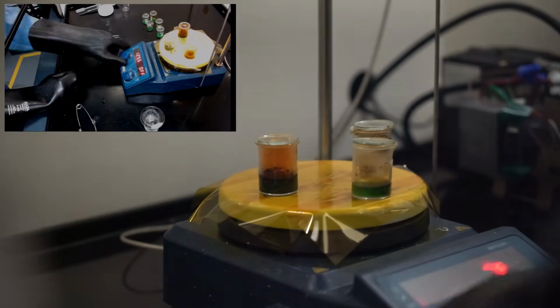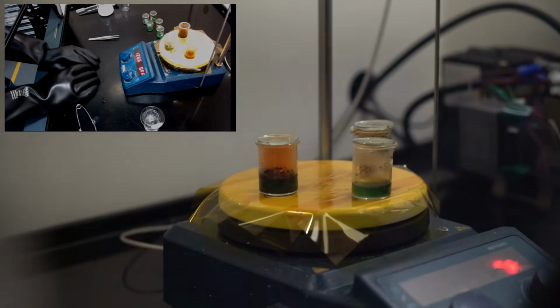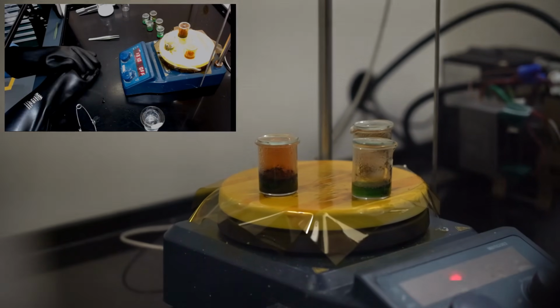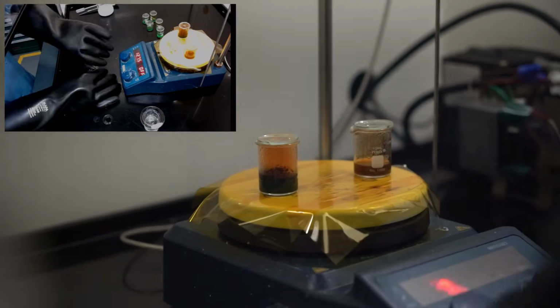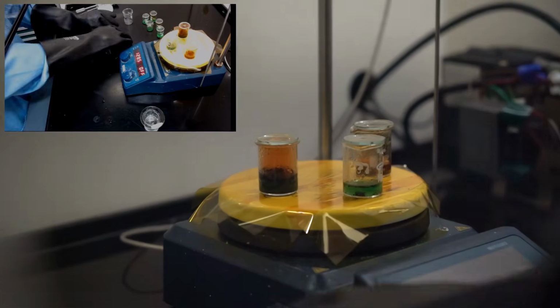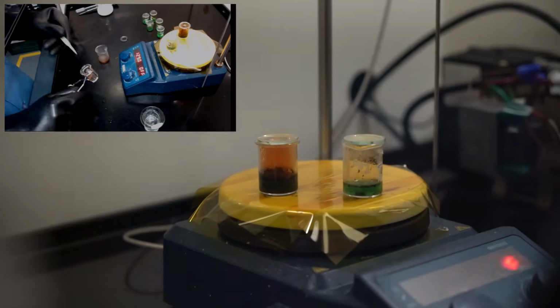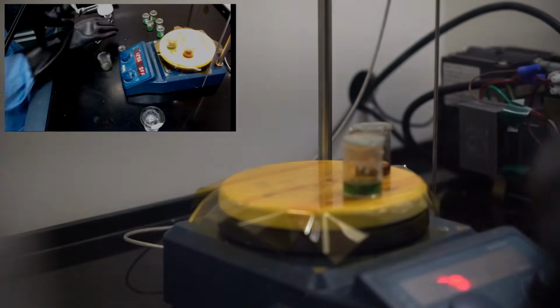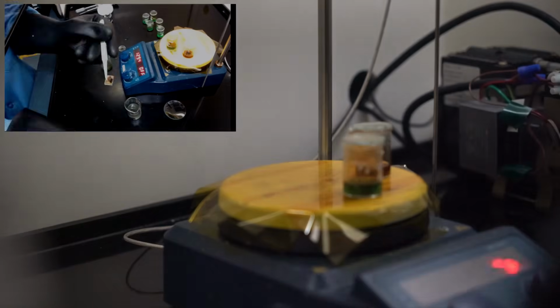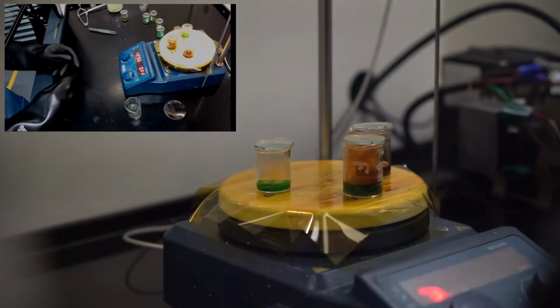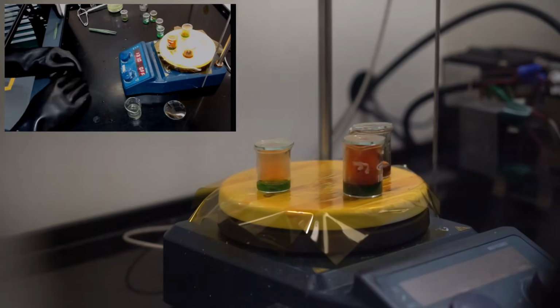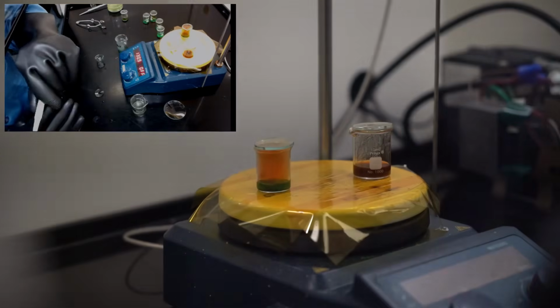Also, I'm using a ductless fume hood, so you'll notice most of the beakers have watch glasses over them just to retard evaporation. This both reduces acid loss in the small beakers so that you don't have too much boil off, you get a reflux going on, and it also leads to the filters wearing out less quickly since you're not dumping quite so much nitrogen dioxide into them. Instead, you end up boiling off water, and some of the nitrogen dioxide will dissolve back into it and drip back in, and you end up with a continuous reflux, and not a whole lot of acid is lost.